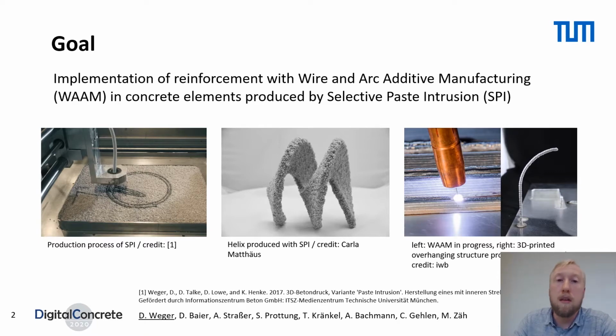The helix in the middle exhibits which complex structures can be made by the selective paste intrusion process, and the wall thickness here is 1 centimeter. On the right side is a picture taken during the wire and arc additive manufacturing process where the welding head deposits the electrode on the substrate. Next to it is a picture that shows the ability of overhanging structures which can be produced with this technique. These examples show that the combination of these two techniques enables a load path optimized construction of reinforced structures and new ways of saving building material.